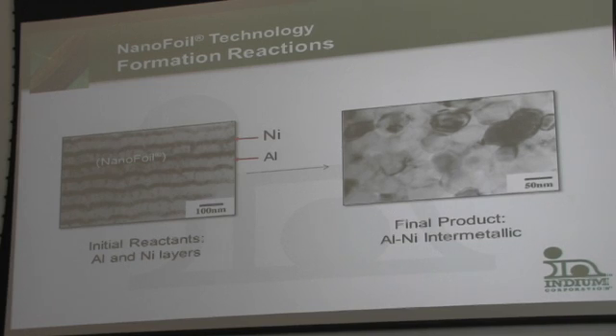And I know very few physicists, but the amount of heat energy within something very thin is necessarily very small, because no matter what temperature you get to, the material itself is almost non-existent. The final product is aluminum nickel intermetallic. So you have this exothermic reaction, this reaction that gives out heat. It's manufactured in a proprietary physical vapor deposition process, a sequential vapor deposition process, where we put down first the aluminum, then the nickel, then the aluminum and nickel and so on in a sandwich form. That takes a certain amount of time.